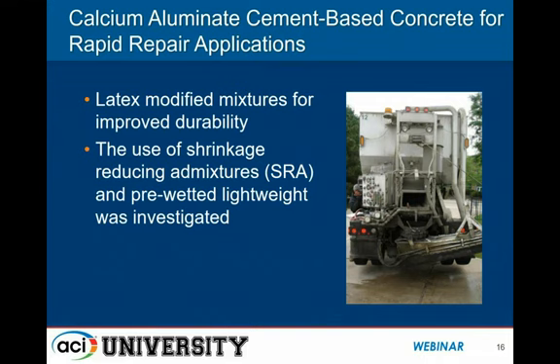And because it was unpredictable and because it was difficult to design for that, calcium aluminate cements were basically not allowed after that for structural applications. But here we're talking about pavement repair and bridge deck repair, and these are applications where the conversion process could be easily accommodated, and the strength loss was not at all significant relative to what was needed from a mechanical standpoint. So that's the first point I want to make. And second, we had a cracking issue that was known to exist in some cases with these cements. And it has a lot to do with the temperature changes that occur at very early ages.